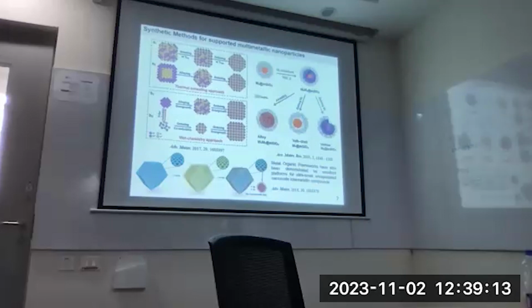So in some cases, if I want to dilute it more or less, I have to form one compound first. Let's say I form platinum 3 tin, or in the case of palladium, I used to make these palladium 2 tin compounds. If I want to make a different, more thermodynamically difficult compound, I have to make this compound first, and then do it in a subsequent step. I cannot do it straight away. It's not a direct way. But these reactions are not very complex. I only had to do some initial trial and error around the initial temperature required. Then it's very easy to make once you decide which compound you want. And they mostly facilitate very straightforward catalytic processes.